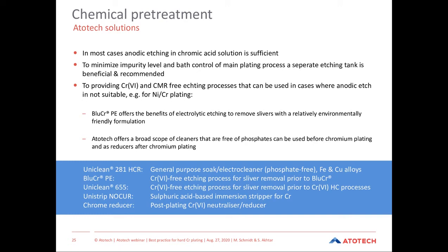As already mentioned, etching is usually the last step before the plating. Today, different options are possible. Typically, the etching is carried out in a chrome 6 containing separate etch tank, which is usually recommended, but some customers also etch directly inside the chrome tank. And with the introduction of the BluCr, etching in chrome 6 solutions is not possible anymore. So Atotech is also providing chrome 6 and CMR-free etching or pretreatment solutions in order to prepare the substrate also for these new types of processes.